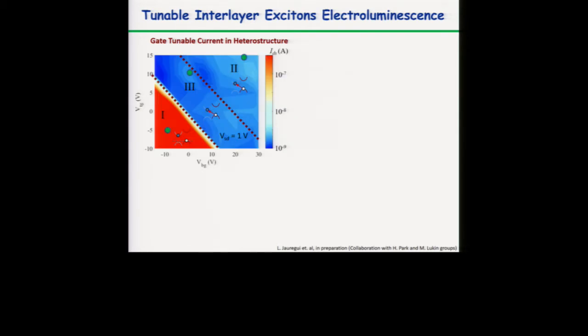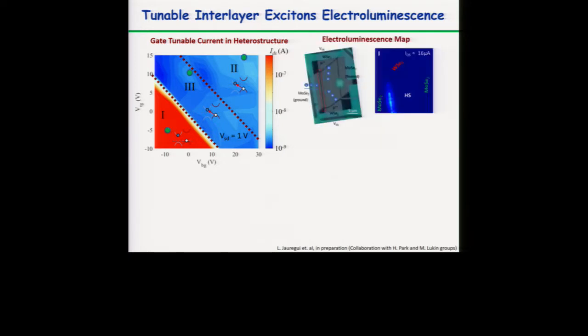But also bear in mind that these are p-n junctions, so these are materials that are mostly holes or electrons. So we can apply current across this p-n junction. This is a color plot of the current versus the top and bottom gates. If we apply current on this p-n junction, we can also obtain electroluminescence. So we can get light out of it, like an LED at the end.